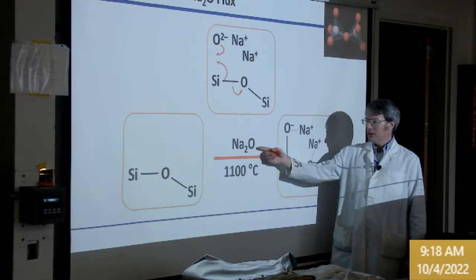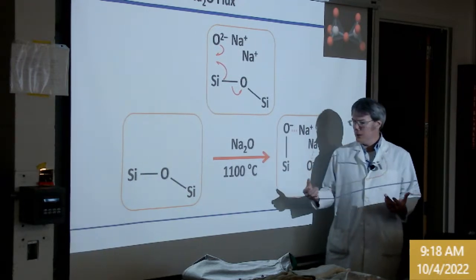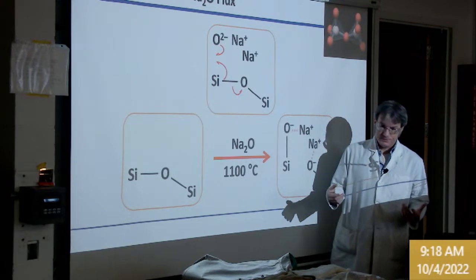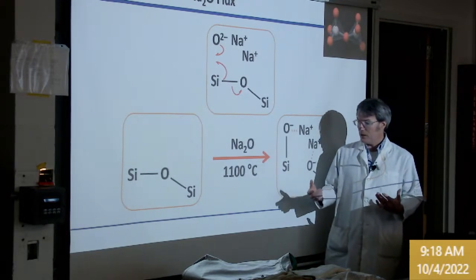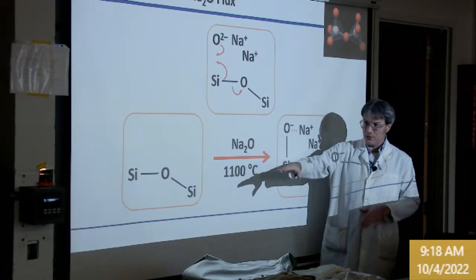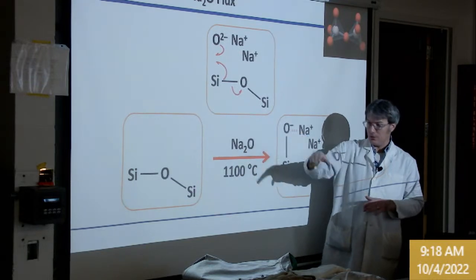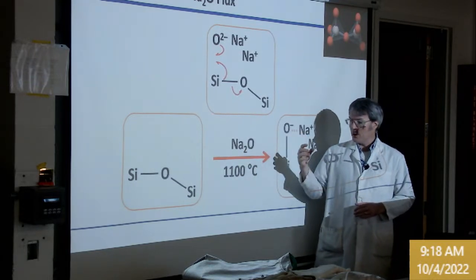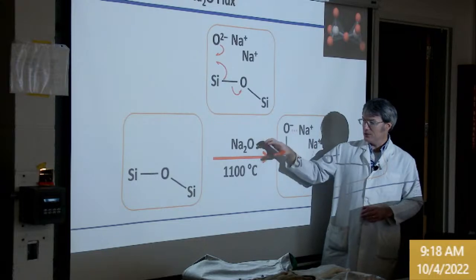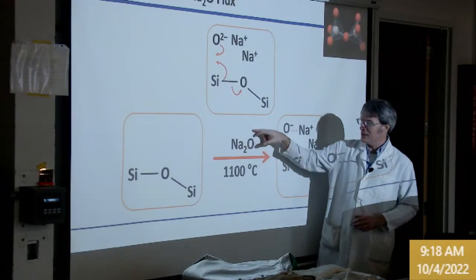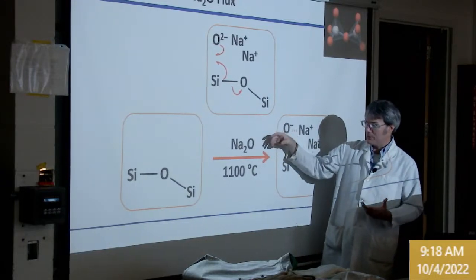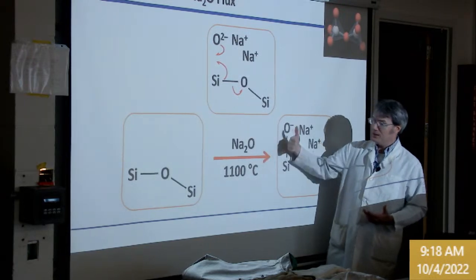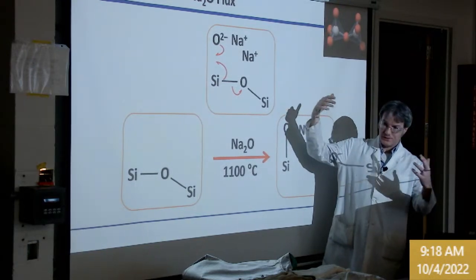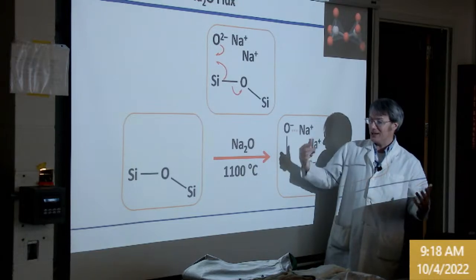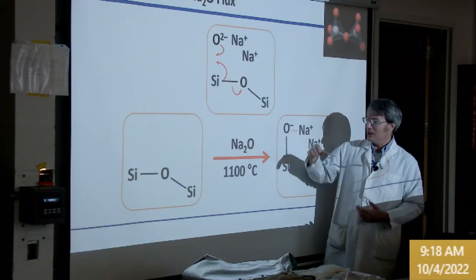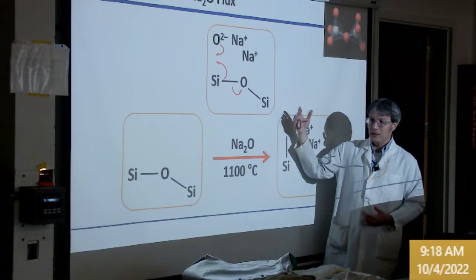Now you might be thinking, well, I thought we put in sodium carbonate. You did. And at around 800 to 900 degrees on the way up to its current temperature, the carbon and two oxygens from the carbonate, Na2CO3, that's washing soda, sodium carbonate, the carbon dioxide left and outgassed. That's a process called calcining. We calcined that and we removed the carbonate.